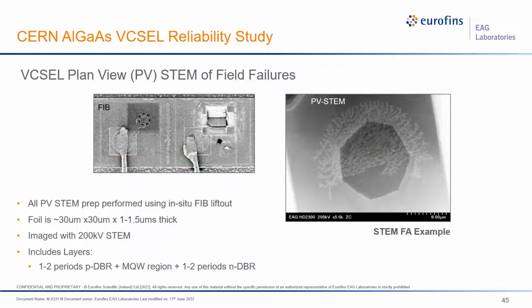The image on the left side of this slide shows two VCSELs. One of those two, the one on the left, is as received, and the one on the right has been cut by a focused ion beam to lift out a thin section of the sample for STEM imaging. The imaging on the right side of the slide shows a plan view of the oxidized AlGaAs aperture in which you can start to see a large DLD network. That's the light, fractal light pattern that is formed, resulting in device failure.